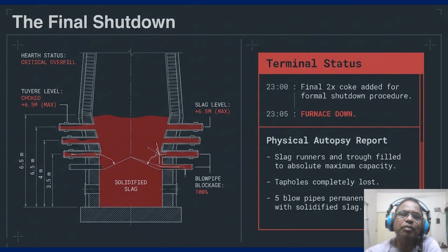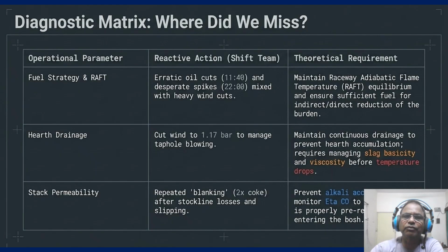So to prevent this from ever happening again, we have to look at the diagnostic matrix to see exactly where we missed the mark. The diagnostic matrix, which is also very important, shows where we missed. This is our forensic breakdown. Look at the fuel strategy row. The shift team made erratic oil cuts followed by a desperate spike. Theoretically, they should have maintained a Raceway Adiabatic Flame Temperature or raft equilibrium. For hearth drainage, they cut the wind to manage the blowing, but they should have been managing slag viscosity before the temperature drop.